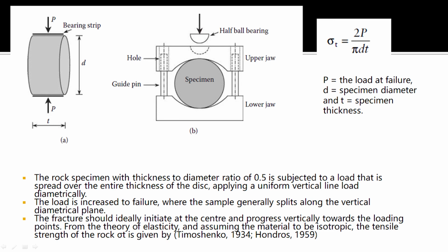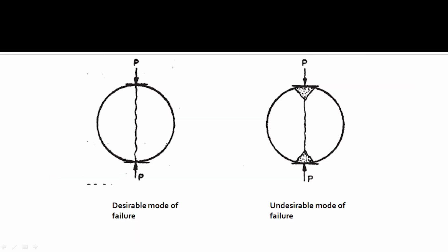Ideally, for an accepted Brazilian tensile strength test, the fracture plane should be parallel to the direction of the applied stress, and there should not be any indentation in the sample. So here the image to your left is a desirable mode of failure, and the image to your right shows a certain amount of indentation before failure. So this mode of failure is undesirable for Brazilian tests.